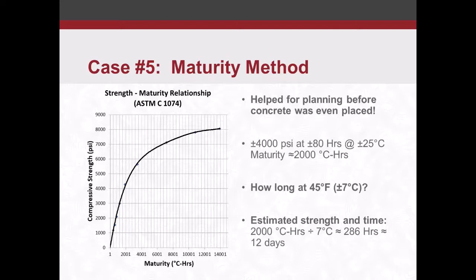And then we got to talking with our client, and we realized, geez, if we know the curing temperature, we can figure out about when it's going to reach 4,000 psi. We got our 2,000 degree hours. If we know it's at 45 degrees Fahrenheit or about 7 degrees Celsius, we just take that 2,000 degree hours, divide it by 7, and you get about 286 hours, which is 12 days, which really helped the contractor to do some planning.